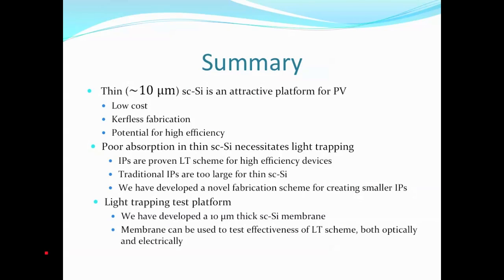So in summary, we want to use really thin crystalline silicon for light trapping, for photovoltaics, because it's low cost, we can fabricate it without wasting silicon, and there's potential for high efficiency. So poor absorption in thin silicon requires us to implement a light trapping scheme.